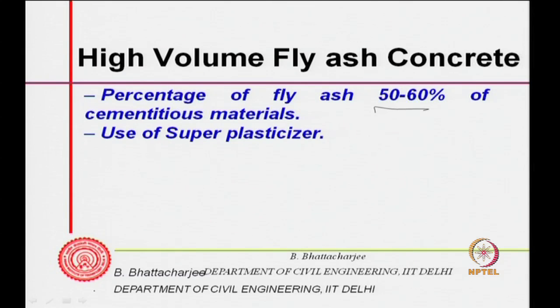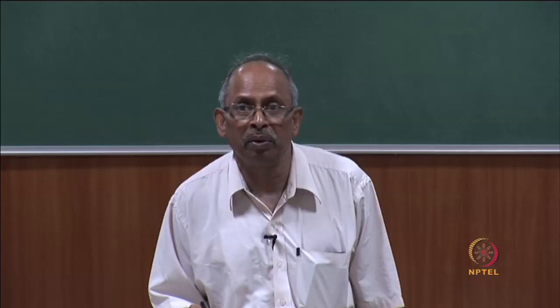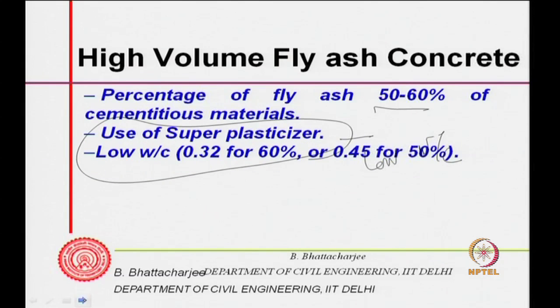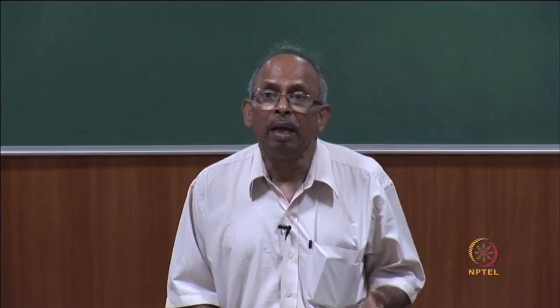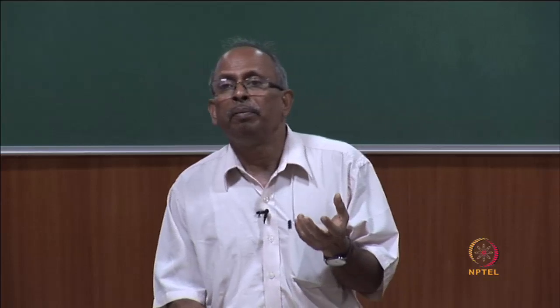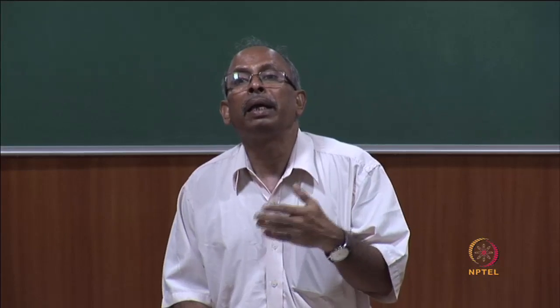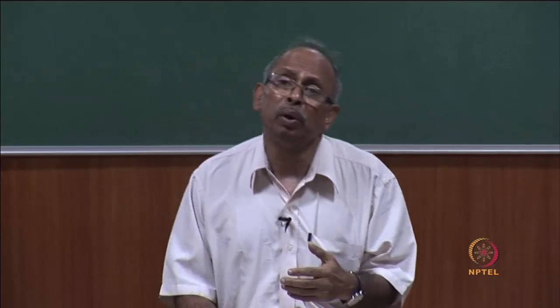But how do you use this to get structural grade concrete, 20, 30, 40 MPa concrete? Use superplasticizer to cut down on your water, and use a low water to cementitious ratio. Therefore, initial strength will be given by the cement. So, 0.32 for 60% fly ash, 0.45 for 50% fly ash. Use a superplasticizer to get the workability. In fact, fly ash, because of its spherical shape, as we have seen earlier, acts somewhat like a water reducing agent. It cuts down your water demand.